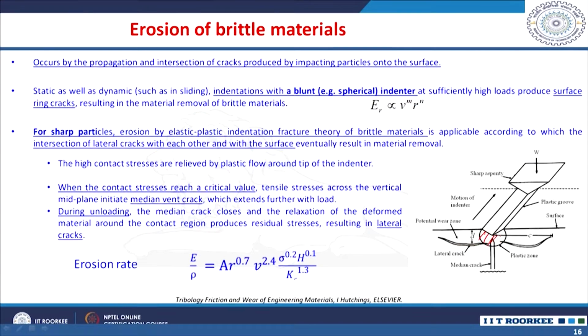So, when high contact stresses are relieved by the plastic flow around the tip of this indenter, I mean the particle with a sharp edge, when the contact stresses reach a critical value, tensile stresses across the vertical mid plane initiate this median vent crack, which extends further with the load.